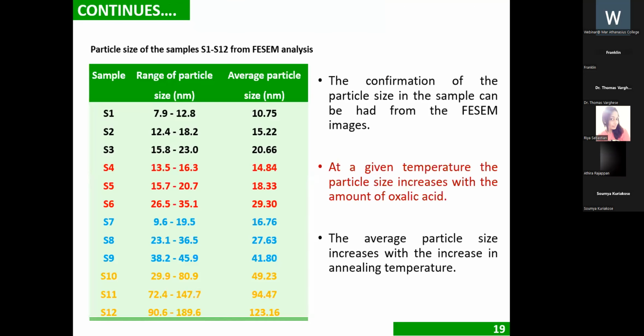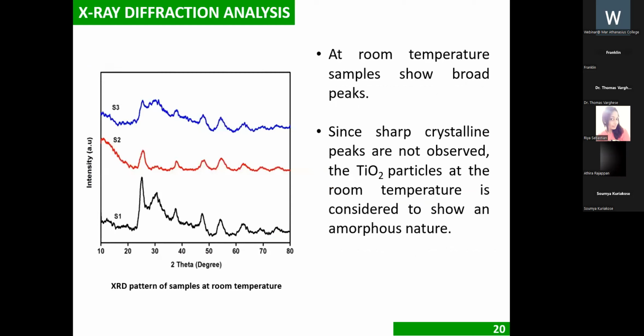for all the samples. And the average particle sizes of the different samples are listed in the table, and it can be seen from the table that as the annealing temperature increases, the average particle size increases. And at a particular annealing temperature, with the increasing amount of oxalic acid, an enhancement can be observed in the particle size also. Then X-ray diffraction characterizations were carried out, and the XRD pattern of the sample at room temperature is